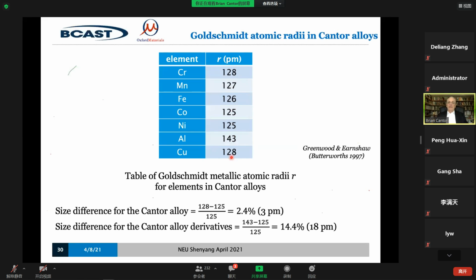If you add aluminium and copper into the Cantor alloy, you can't add it in equal proportions, but you can add about 5% of aluminium and you can add about 10% of copper into the Cantor alloy and still keep a solid solution. And that's because the size difference has got bigger. But remember, 3 picometers in the Cantor alloy.